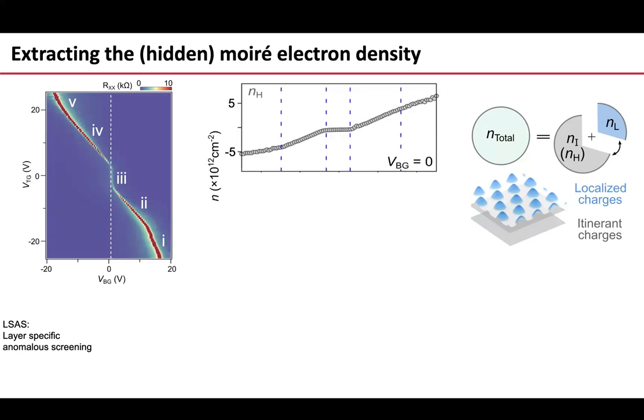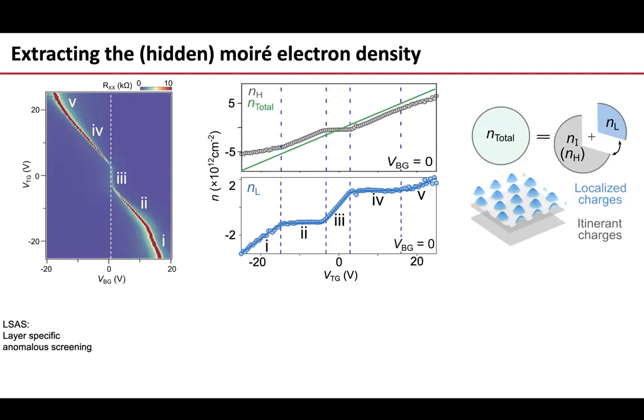How much charge? You can measure the Hall density as a function of gate-induced density. This is a cut along that line. You can see that in these regions, 2 and 4, we're adding charge to the system as expected. In region 3, the Hall density remains fixed, which is consistent with the itinerant system not changing. So if you trust that electrostatics works and your gates are inducing the charge that we know they should be inducing, then you can just subtract what you're measuring from the total gate-induced charge and you get the localized carrier density. In regions 2 and 4, it's flat because there it's working like it should. And in regions 3, 5, and 1, it's changing because it's the localized system that we're charging.